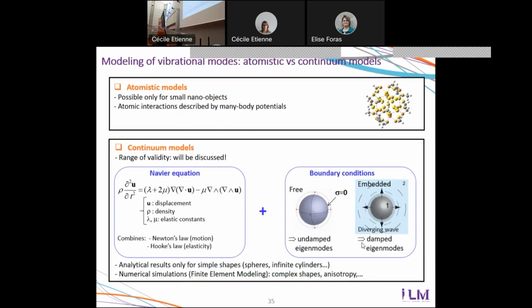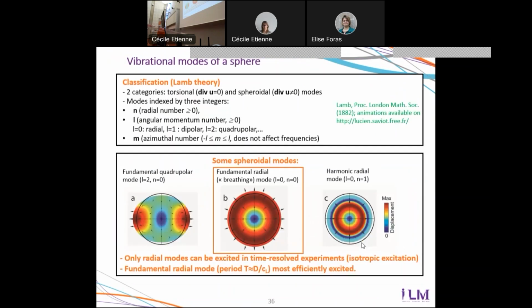So to understand where it comes from, one has the choice between two main approaches for discussing vibrations: atomistic models, in which all the atoms forming a nanoparticle are taken into account, and their motion is solved for interactions described by potentials. And one can also use continuum models, in which the atomistic nature of the nanoparticle is not taken into account. They are described as a continuum medium. And what is solved is the Navier equation, which relates the temporal and spatial derivatives of displacement, that is, locally, what is the deformation as compared to the equilibrium position.